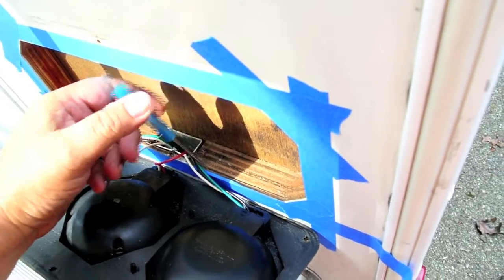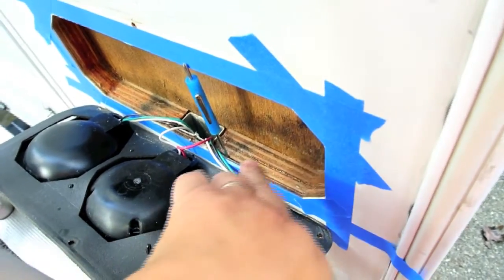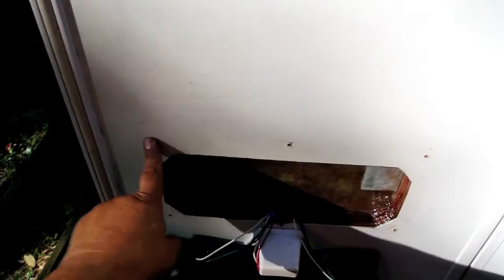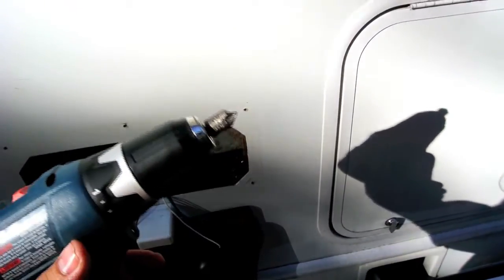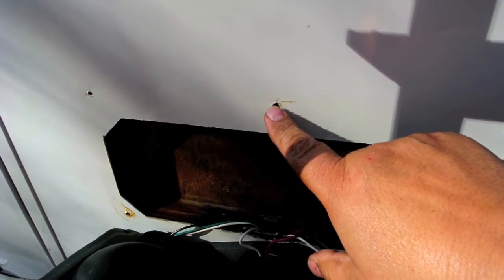So what I'm going to do is I'm going to put that screwdriver in there and I'm going to pour some epoxy in there and then pull it out so it won't get epoxy sealed inside. Part of the reassembly is I want to clean up some of these holes because the fiberglass has kind of been fractured there a little bit when they drilled the holes. There's a trick to doing that: you just take a countersink bit but then you run it backwards instead of forwards. When you do that it does not further crack it. One way to prevent this kind of cracking is when you're drilling the hole, if you run it backwards until you're through the fiberglass then turn it forward, you won't crack them.